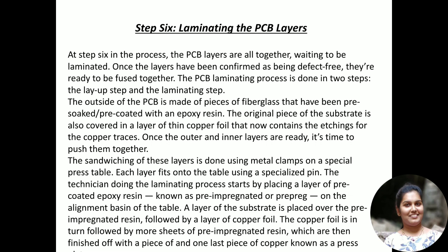they are fixed properly. If all the layers are fixed properly, the PCB stack is taken to the next press, that is a laminating press. The laminating press uses a pair of heated plates to apply heat and pressure to the stack of layers. The heat of the plates melts the epoxy inside the pre-preg. It is the pressure combined with the heat that fuses the stack of PCB layers together.